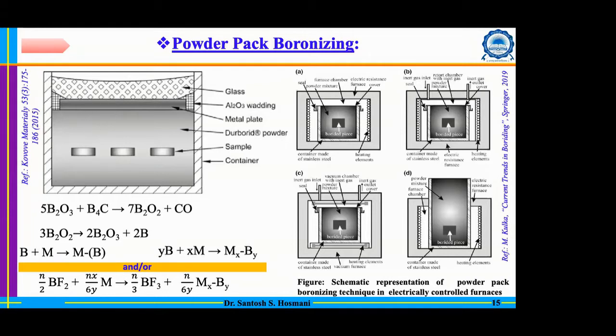The major reaction in this container is basically the reaction of the boron source, that is B4C, and it is believed that in that boron source you have some boron oxides also. These boron oxides play a role as an activator. The reaction between the boron source and this boron oxide leads to the formation of a boron oxide having a different stoichiometry, and that stoichiometry has a lower stability. That means there is a possibility that that oxide will go back to its original oxide form, leaving behind boron in the atmosphere. That boron will be the adsorbed boron, and then it will react with the metal surface, forming metal boride. That is the mechanism people have proposed.